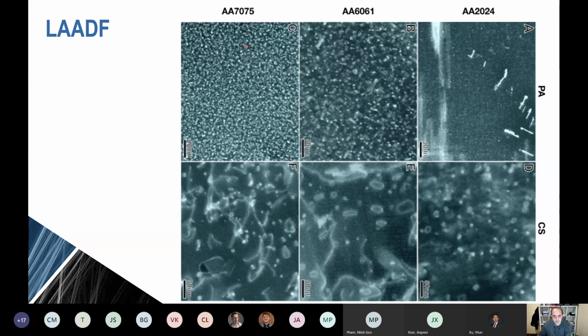So if we look at the 7075, this first image up here, this is the traditional precipitate microstructure in the peak age state. Actually these are all eta prime particles, a very high number density of them. This is the 6061. In this case, you're looking down the 001 zone axis, so you can see the rods in 2 directions. This is the beta prime phase. And in 2024, again, this is down the 001 zone axis, and that very fine distribution there is a very fine distribution of S phase, Al2CuMg. And so these are our traditional peak-aged microstructures, showing precipitates that result from elevated temperature thermal treatments.